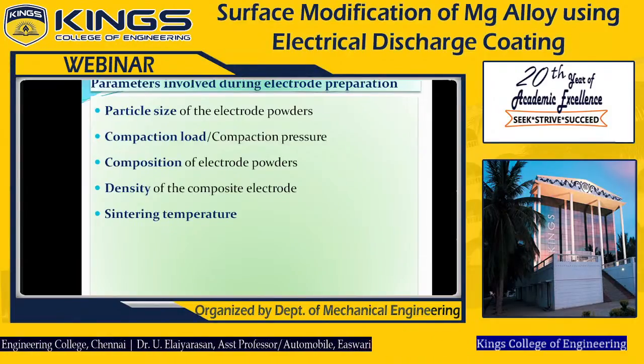And then sintering temperature. After the electrode is compacted, there will be a green compact. If you want to increase the bonding strength of such electrodes, the sintering temperature is very, very important. If we sinter the electrode, we can enhance the bonding strength of the electrode. Further, we can use it for the EDC process.